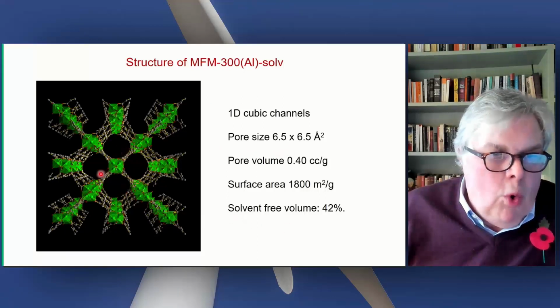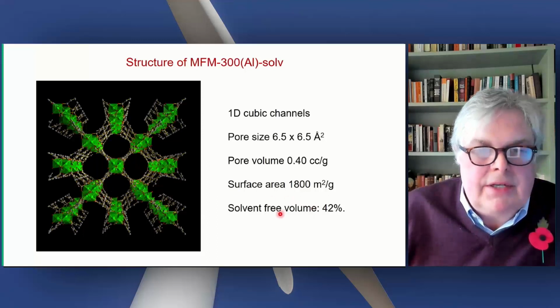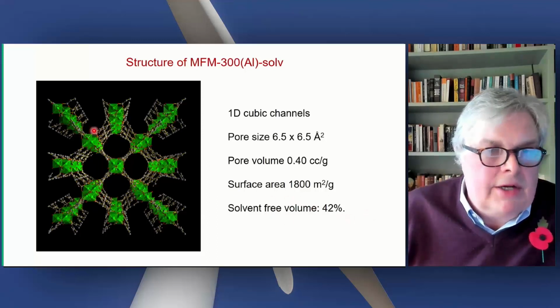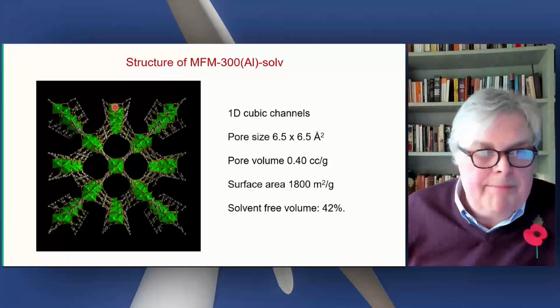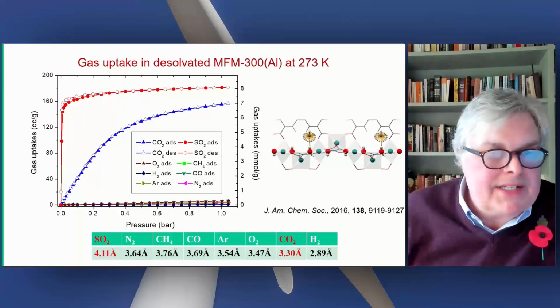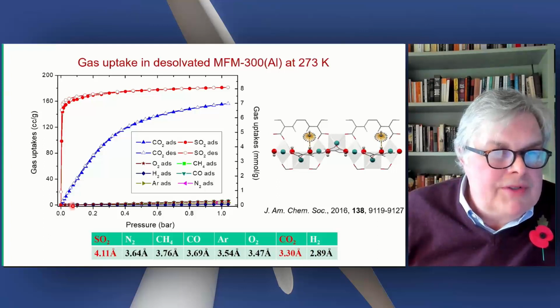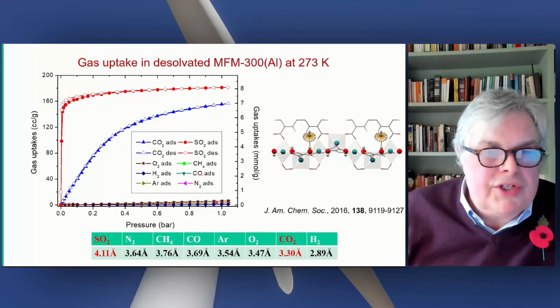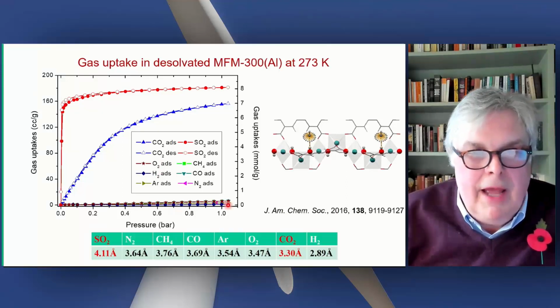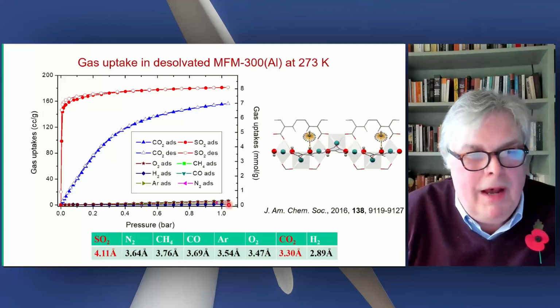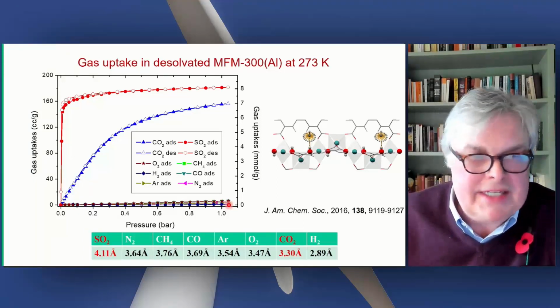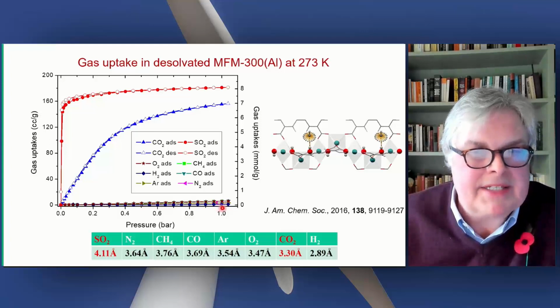Once you remove the water that is in these channels, 42% of this structure is just vacant and available for substrate binding. So you look at the gas isotherm, you introduce all these gases, nitrogen, CO, methane, hydrogen, argon, oxygen. They're basically all down here near the baseline. If you want to make a really, really poor hydrogen uptake MOF, this is the one. It has very low capacity.